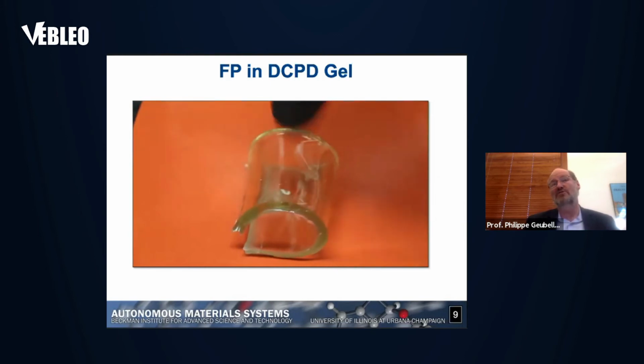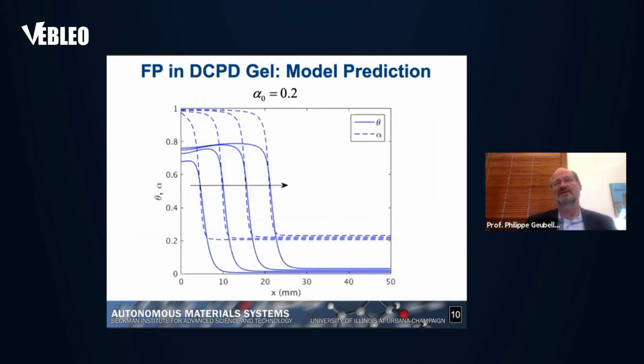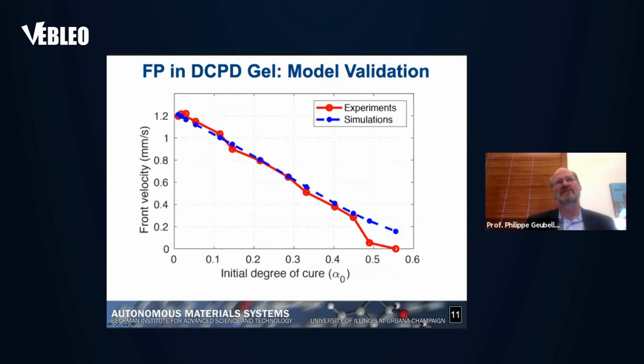So we can actually model this also using the equations that I just described before. In this case, the initial degree of cure is 20%, 0.2, and we can see that we also get a front that propagates. But what we observe numerically and experimentally is that the front propagates slower when you propagate it in the gel, and it makes sense, right? Because some of the energy has already been used. And so what you have here is a comparison between the simulation and the experiment for the front velocity as a function of the initial degree of cure.